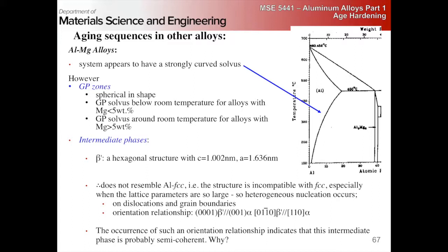Why is it going to be a spherical particle in the absence of strain? Because the sphere minimizes the surface area per volume, right? Even though it's still a coherent interface, there is still a penalty to pay, right? An interfacial energy, right? So a sphere will always minimize that, right? Classic bubble physics, right?